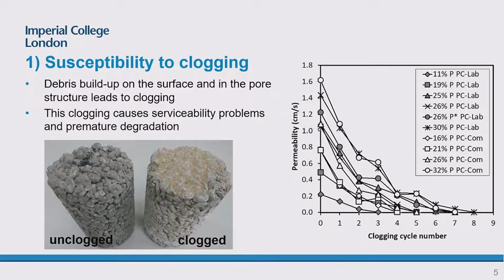First of all, let's have a look at some of the data that we have in terms of susceptibility to clogging. This is the buildup of debris on the pavement over time. We have the pavement as cast on the left-hand side, and over time, as the pavement is in service, it gets exposed to sediments like sand and clay, which are the most detrimental ones, and it blocks the pavement. We've done a lot of testing on not only laboratory-prepared pavements, but also commercially available ones, and we've exposed them to accelerated clogging tests, simulating what these pavements would be exposed to over their service life. You can see, depending on the pore structure of the pavement, between 11% to 32%, you get clogging between 3 cycles and up to 7 to 8 cycles.